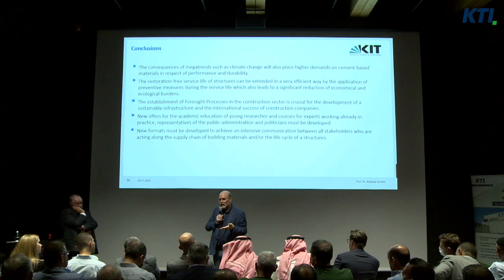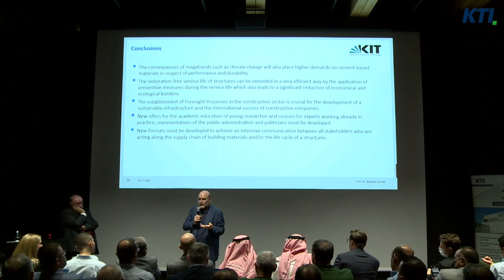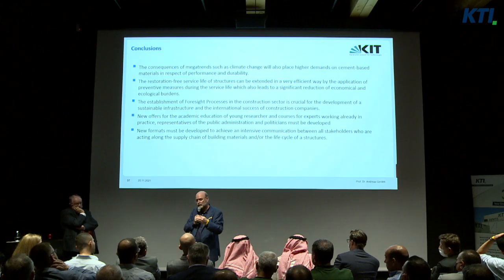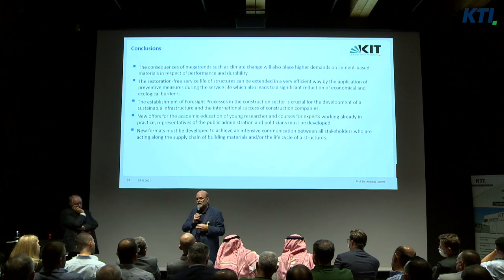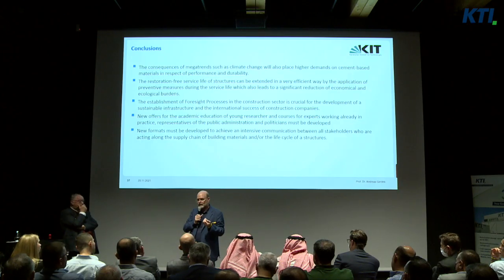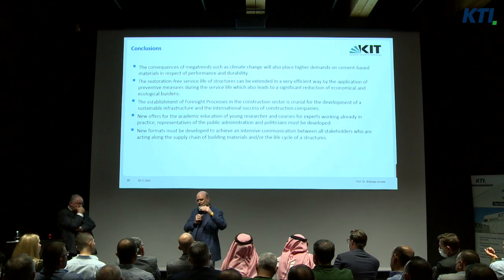And it can be applied easily. You can spray it on the surface. The reinforcement is no problem because the penetration depth is only 6 millimeters, so of course there's no interaction with the reinforcement. And if you are lucky, due to the fact that no longer water penetrates, there's a drop in the water content, and if there's a dry atmosphere like here, that stops the corrosion process. We observed it in practice, but it's not really a scientifically based method to prevent corrosion. But it helps to stop corrosion processes.